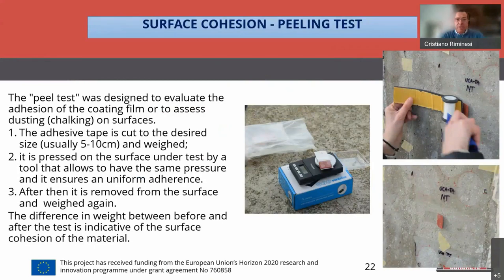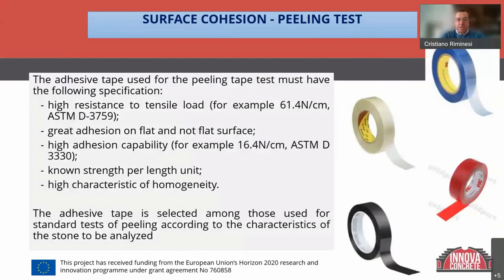In order to control the surface cohesion, we use the peeling test. It is composed of a quite simple adhesive tape that can be applied on the surface in order to perform a uniform pressure and so obtain a uniform adhesion. We can use this simple tool, and by the measurement of the tape before and after the adhesion, we can understand the entity of the material detached by this tape, and so the cohesion of the surface.